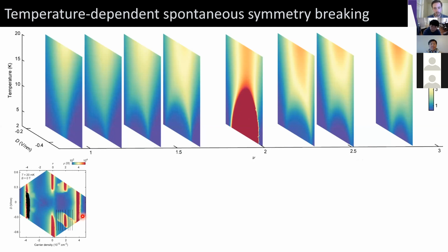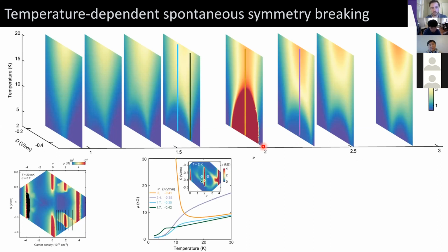Now, what happens if I detune from half filling? In this case, I still see the arch-like feature, but it gets smaller. This arch-like feature gets smaller and eventually disappears as I detune too far away from half filling. And also, the arch-like feature is metallic. It's no longer insulating. So I can take a few cuts to show you the temperature dependence to illustrate this. If I take a cut precisely at half filling here, you see a standard metal-insulator transition owing to the formation of this correlated insulating state below about 13 Kelvin.